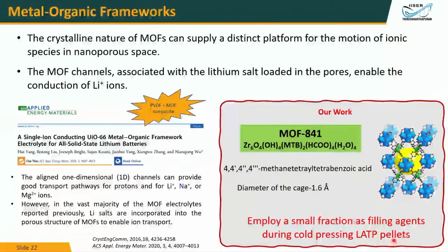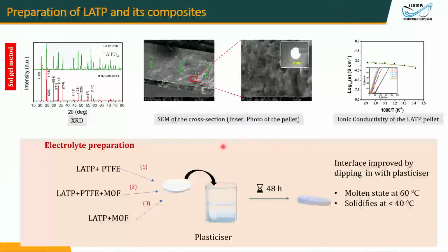So we just added a small fraction of these filling agents during our pellet pressing process, and then we assembled a cell. We did not want to go for a high temperature sintering. We just stopped at a place where we were able to see good XRD peaks of LATP, and we did not go to a high temperature sintering, which is the advantage. And then we also mixed it with a little bit of PTFE. PTFE is Teflon. So we added a little bit of LATP and PTFE, where PTFE acts as a binder here, and also an absorbent, and LATP PTFE MOF is another composite, and LATP MOF is another composite. So these were the 3 different systems we tried.